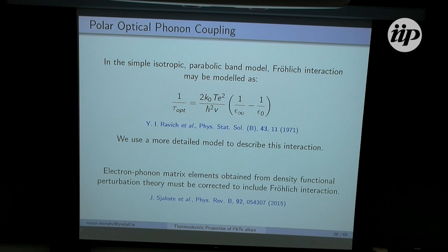Now, getting back to this, I want to talk a bit about another type of electron-phonon interaction, which is polar optical phonon coupling. To give you a sense of what we do here, we use a model to describe it. It's not this particular model here; this is a very simple model from the 70s in a simple isotropic parabolic band case, where v is the carrier velocity, and epsilon infinity and epsilon 0 are the high frequency and static dielectric constants. By plugging these into the formula, you get your scattering rate for polar optical phonon coupling.